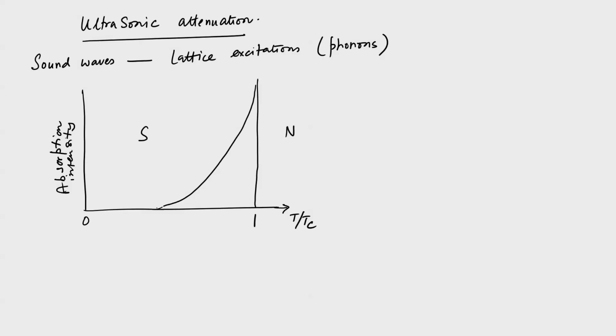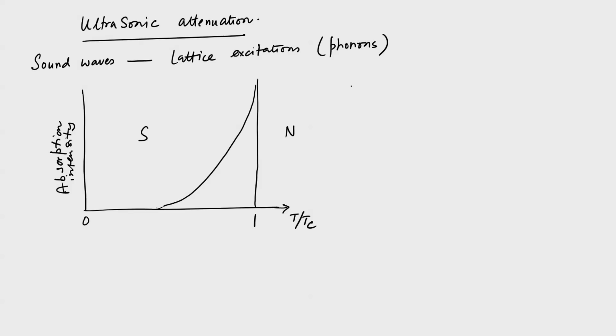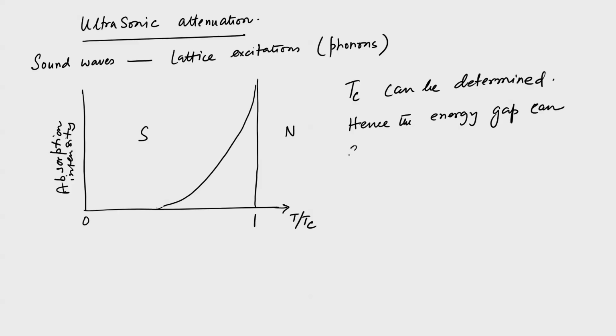So, this gives the idea of the Tc. This is plotted of course as T by Tc, but in actual experiments one does not know what Tc is. So, it is plotted as a function of T, and the Tc can be extracted from this, and Tc, as I said a number of times, is a measure of the gap. So, the gap can be determined. Since Tc can be determined, hence the energy gap is determined.